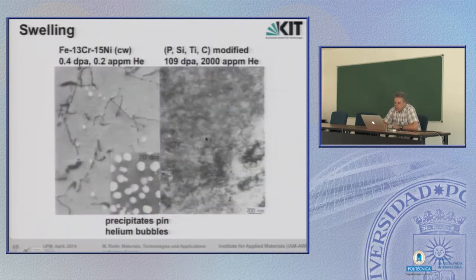Here again, recombination centers. These can be precipitates. In this picture, we have a steel consisting of iron, chromium, and nickel. And already after 0.4 dpa, you see a lot of big voids. And here with 109 dpa, that's several orders of magnitude higher doses, you can't see it from your point, but there are millions of very, very tiny voids. And this is only due to very fine precipitates of phosphorus, silicon, titanium, and carbide. So this is a valid measure to reduce swelling.